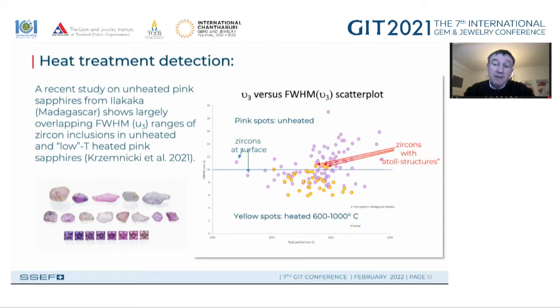And when we add on top of this the stones which have been heated at rather low temperature, which are the yellow points, we see quite a strong overlapping. So it means this criterion for low temperature heating below 1,000 degrees is not a clear-cut situation anymore. It's rather a gray area, an overlapping area. So it does not help us so much in this respect.